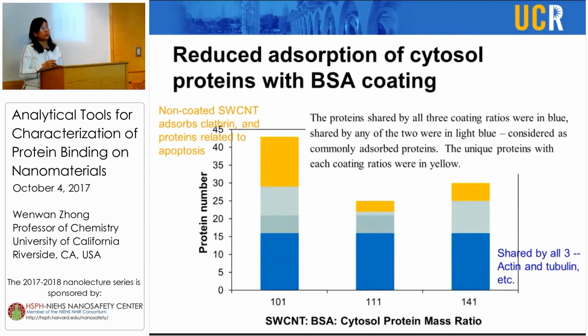And we further identified those proteins and compared the total number of proteins identified in the carbon nanotube that only interacts directly with cytosol protein, or the BSA coated nanotube at the 1:1 coating ratio with one mass ratio of the cytosol protein, or the 1:4 coating tube with the same mass of the cytosol protein. So the blue bar represents the proteins shared by all three preparations. Those seem to be the very strong binding, probably still just attached onto the carbon nanotube anyway. It doesn't matter whether it has BSA or no BSA on the surface.